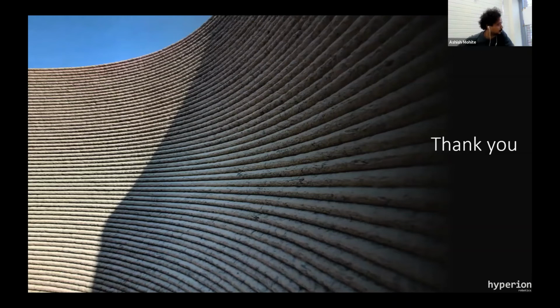But just to give an example, normal concrete, which is, I'm sure, everywhere around you, where you're sitting right now, has 25 megapascals of compressive strength. The 3D printed concrete which we have has compressive strength of 55 to 65 MPa, depending on the dimensions like X, Y, Z. So in certain directions it has 65 MPa, in certain directions 55. It's more than twice the compressive strength of traditional concrete.